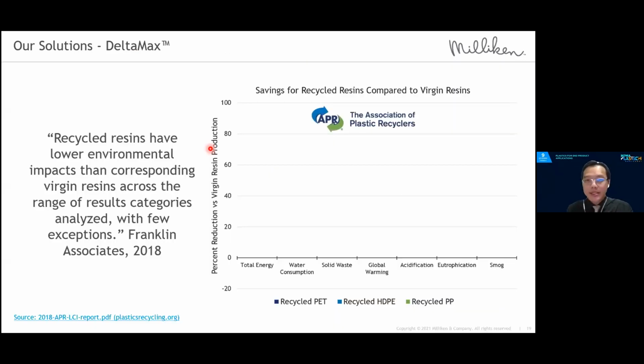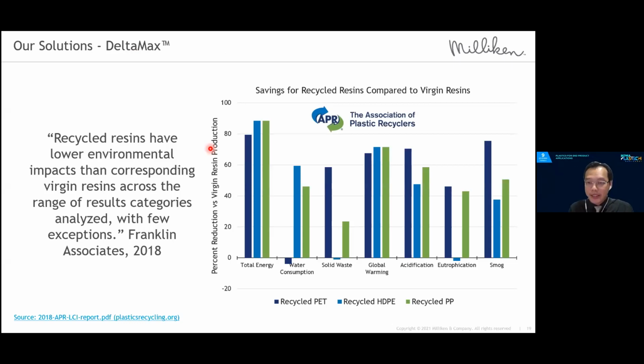And just some numbers here, where we compare recycled PET, recycled HDPE, recycled PP, the percent reduction versus virgin resin production. Basically, any recycle usually is better than the virgin. So this is just some of the data, and we participate in the Association of Plastic Recyclers. The challenge of using recycled is the variability of the incoming stream, and specialty additives like Delta Max can help make it easier to use and, at the same time, like we explained previously, even optimize the processing of recycle itself.